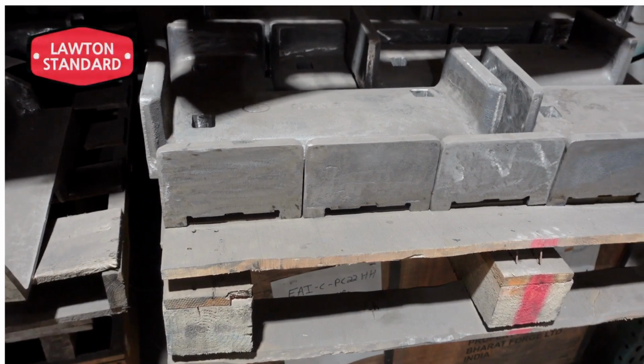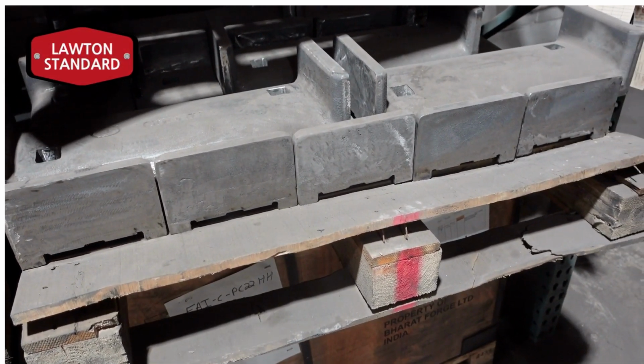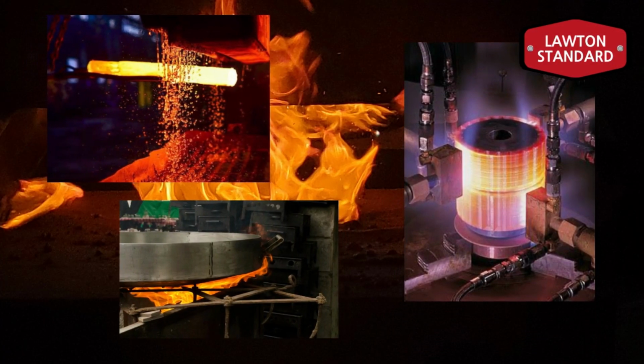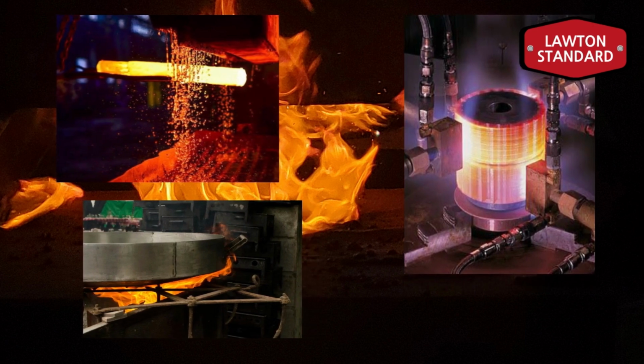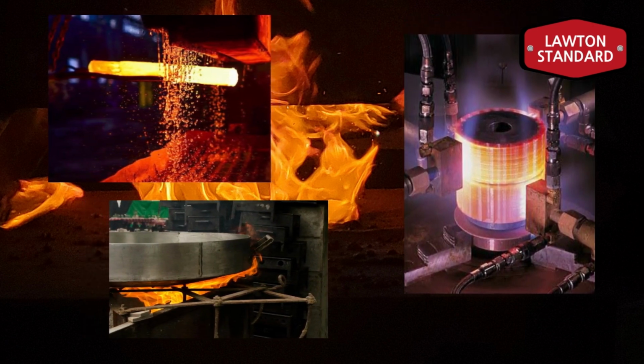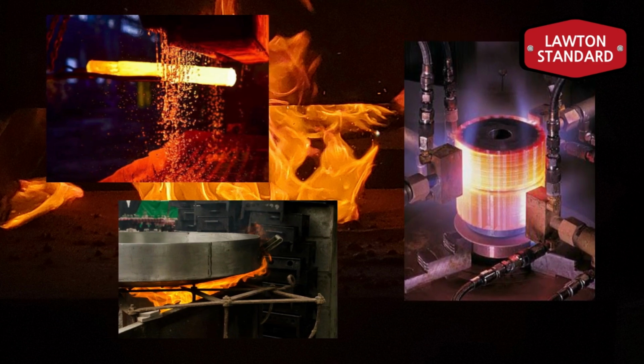So quenching and tempering is another option for white iron, and one of the reasons why people like to quench and temper white iron is it typically turns the austenite that's in the matrix, alongside the cementite and the carbides, into martensite. And what that does is it makes the general matrix harder as opposed to when it's just austenite. Stress relief gives you a little bit more forgiveness in that regard, in that if you do that, the chances of it breaking on you are non-zero, right? But they're less likely.